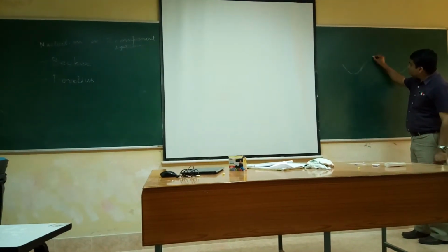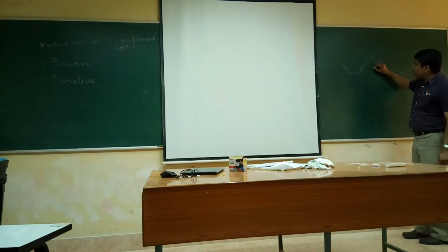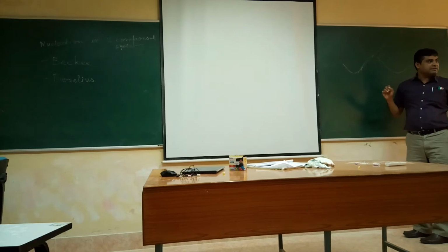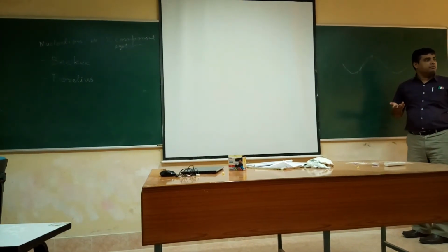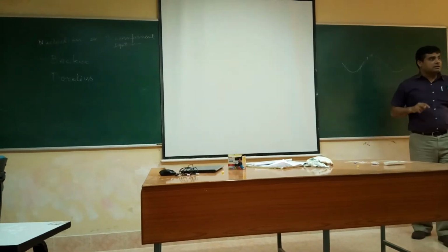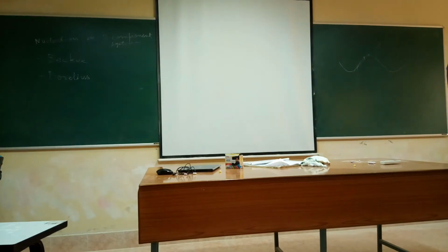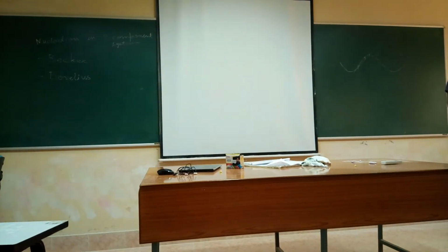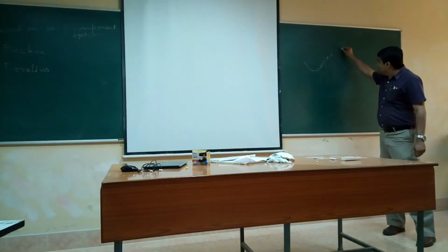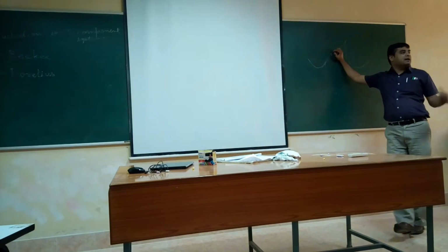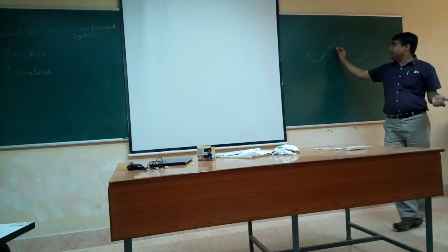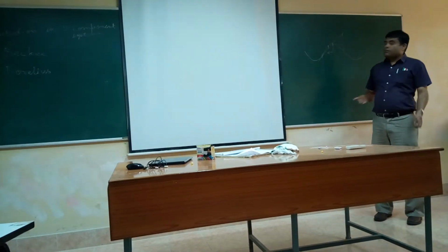We drew a tangent here, and for the Becker model we said that for any composition below this, delta GV will be positive, since delta GV sign was negative of this length. The gamma is positive, so the embryo cannot form at any composition below this, for the Becker model.